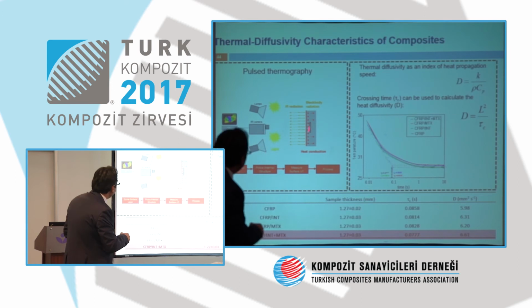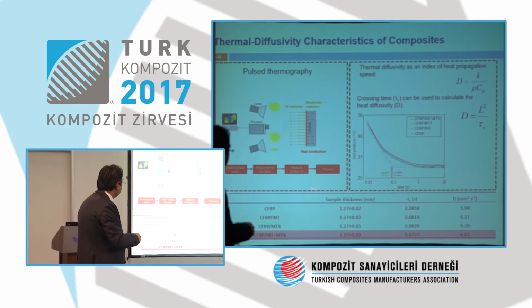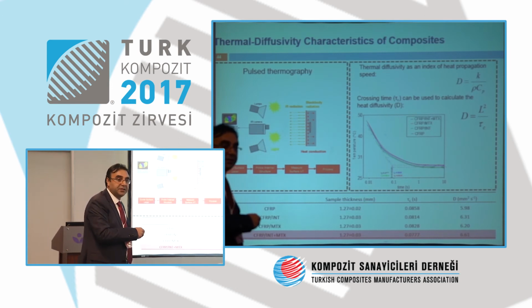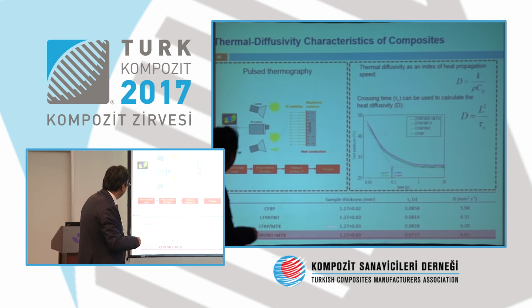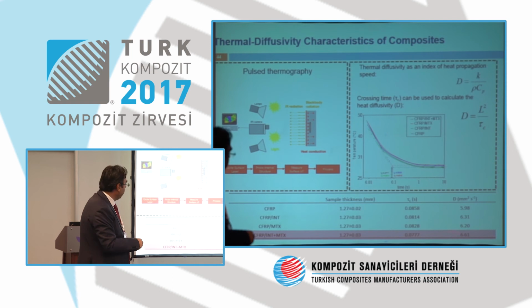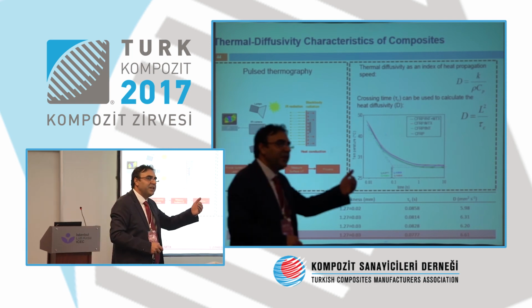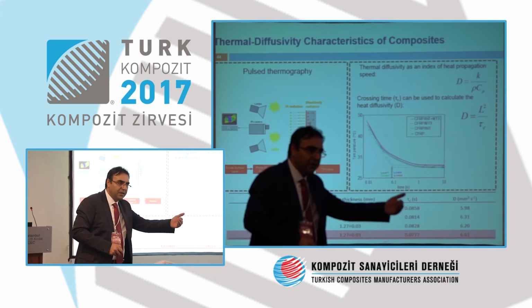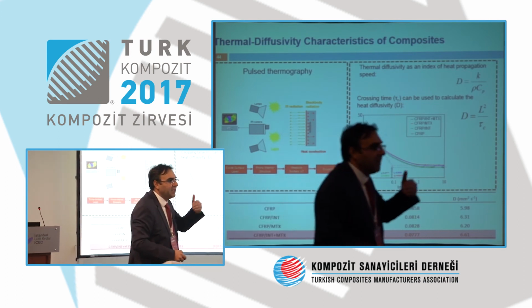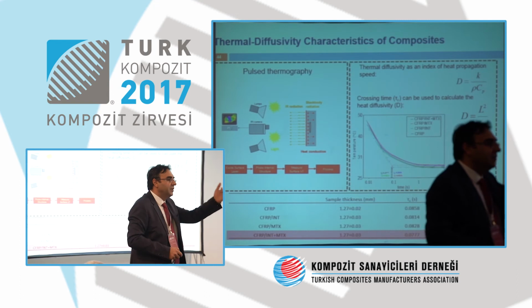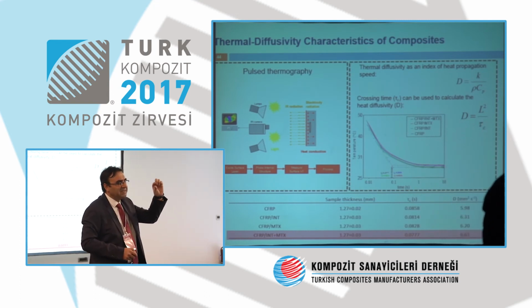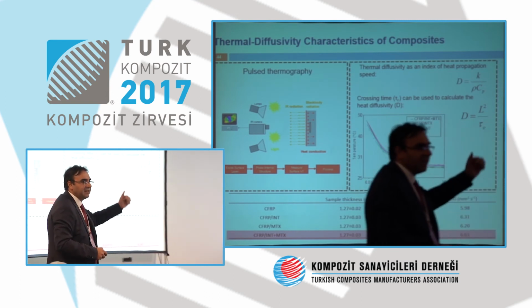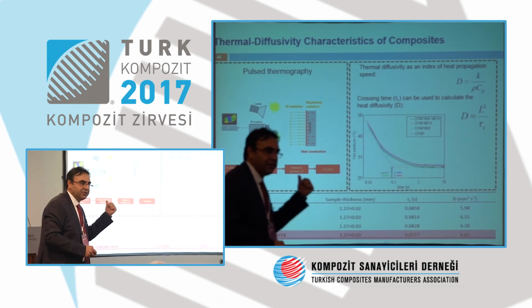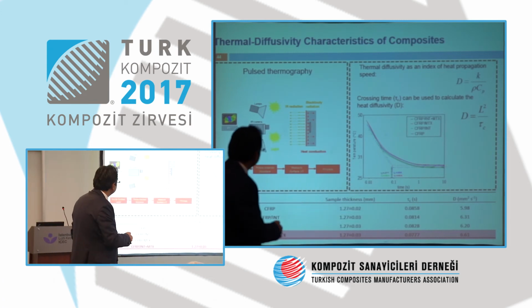And also we look by using the pulse thermography. These are the systems available at the center in terms of the facilities. We look at also the improvement in the thermal diffusivity, and although the thermal diffusivity increases, it is not that high. So by adding graphene, you are not making your material much more thermally conductive. Slightly better results, but not as high as the case of the electrical conductivity.